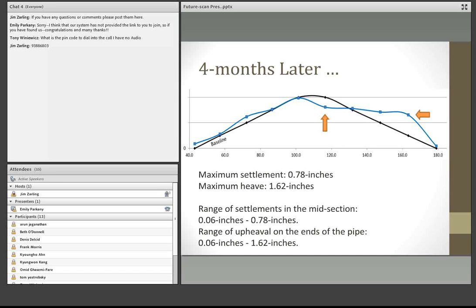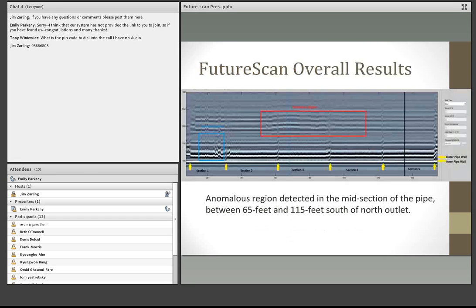If we look at the elevation after 4 months after the pipe was installed, this is what we got. Overall, it showed both settlement and heave. The maximum settlement was about 0.78 inches, and the maximum heave that we measured was about 1.62 inches.